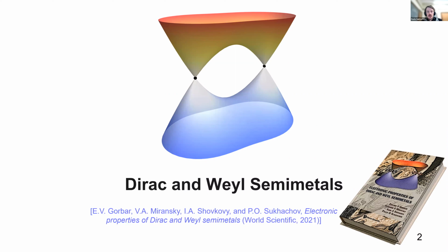Indeed, if we draw a cartoonish description of the low energy spectrum, we will see that it contains a number of so-called Dirac or Weyl nodes, as you can see here. In the vicinity of these nodes, the energy spectrum is linear. It's quite unusual because usually we think that it should be quadratic in conventional solids, but here it's linear.